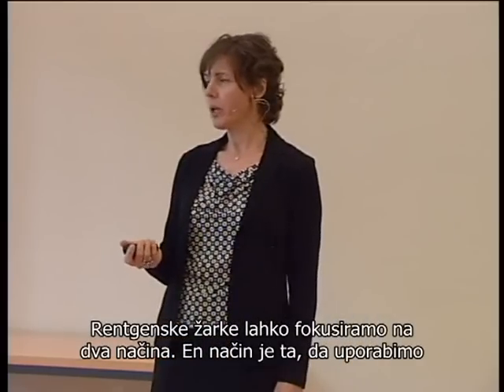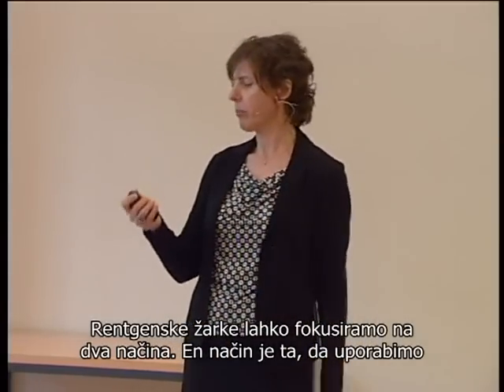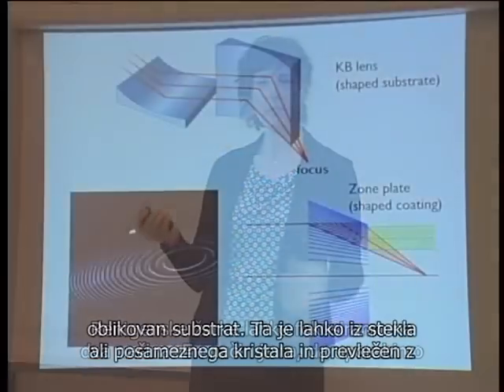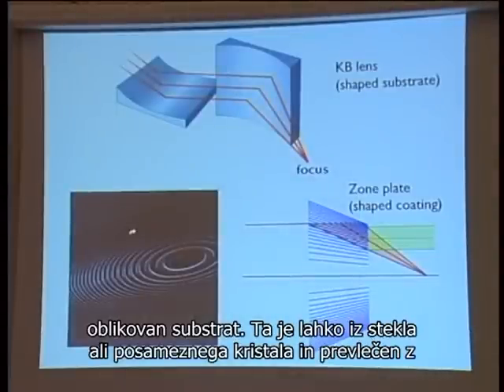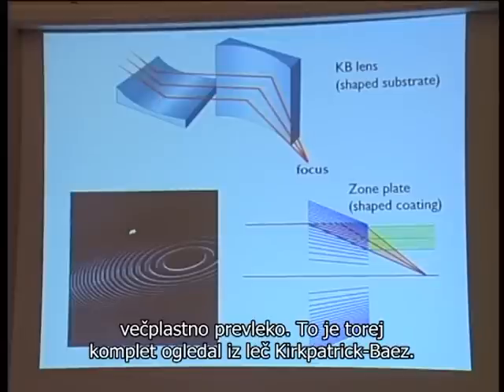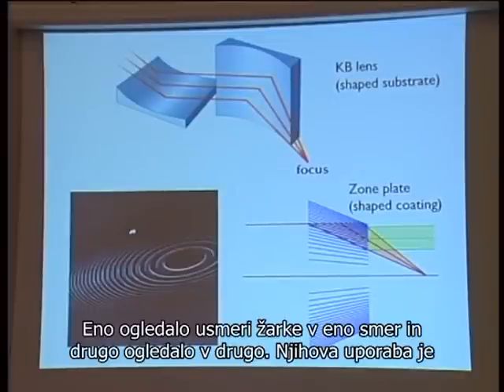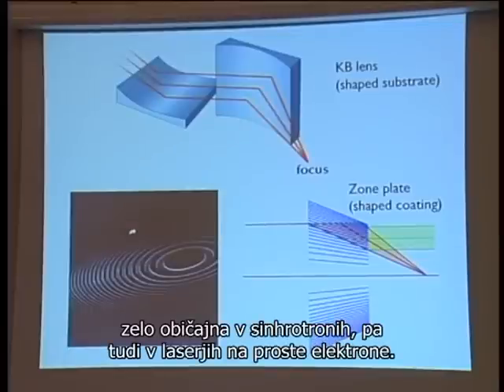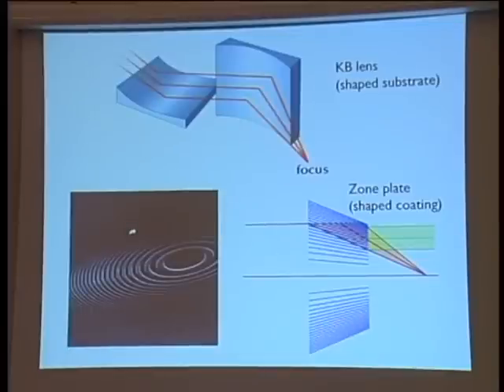So, to focus X-rays, we can do this, for example, in these two ways. One way would be to use a shaped substrate. So the substrate can consist of glass or single crystal, and coat it with a multilayer. So this is a Kirkpatrick-Baez lens or mirror set, where one mirror focuses X-rays in one direction and the other in the other direction. So it's pretty common actually to be used at synchrotrons, but also at free electron lasers.